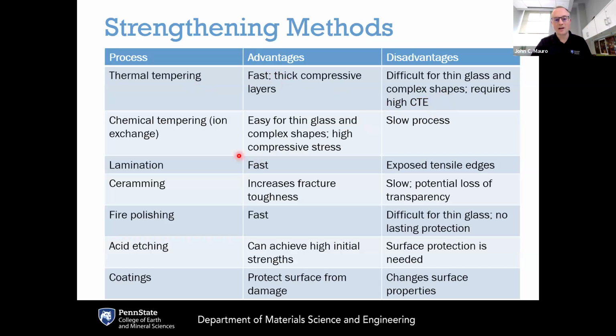Chemical tempering or ion exchange has a number of advantages. This can be done on thin glass, like this is what's used in all your cell phone glass. It can be used for complex shapes. You can get much higher compressive stresses compared to thermal tempering. The disadvantage is that it's a slow process, and that means it's an expensive process. It takes on the order of 8 to 10 hours.